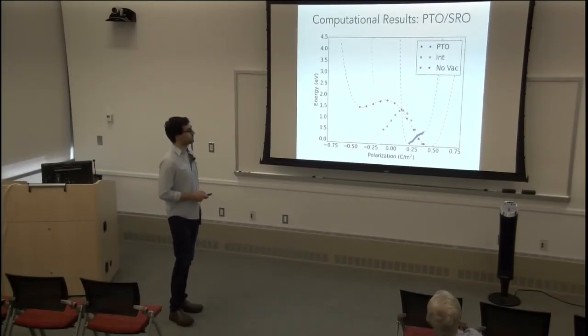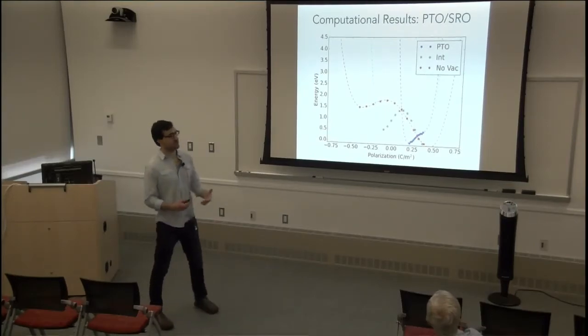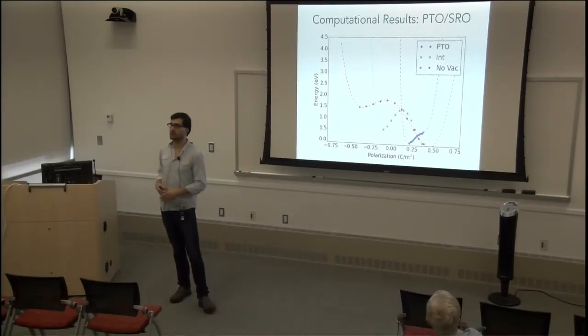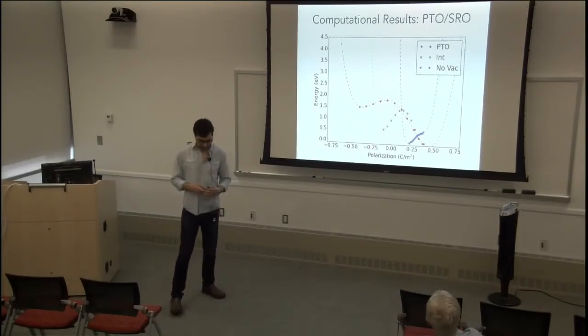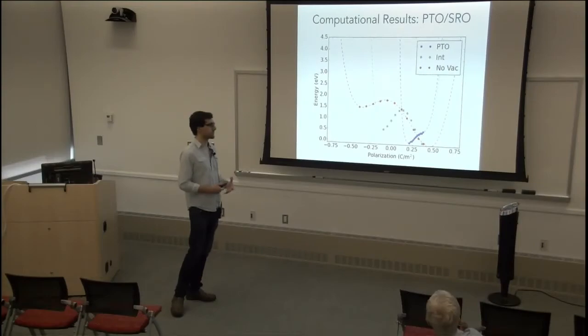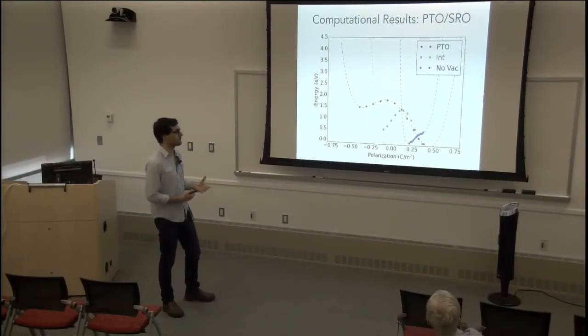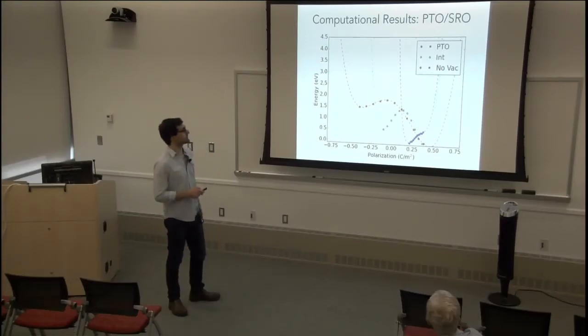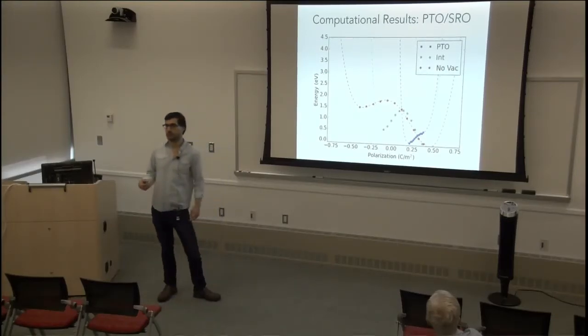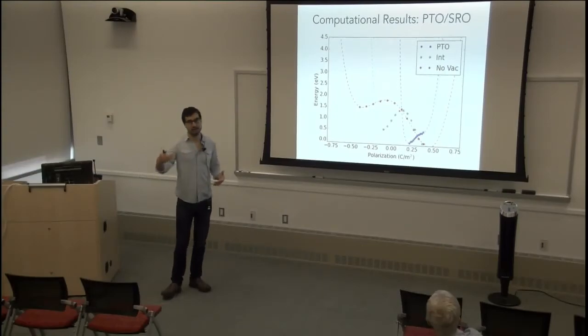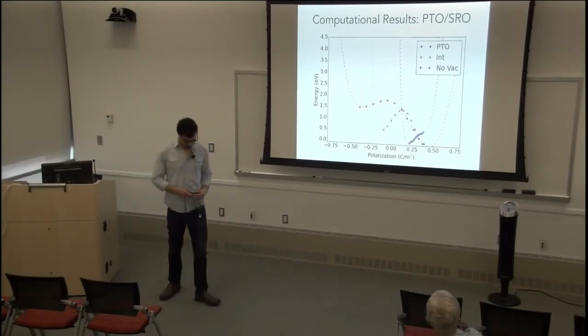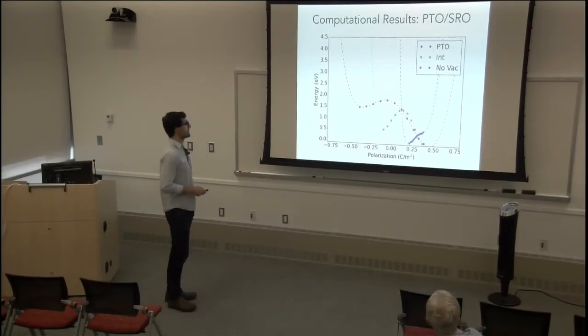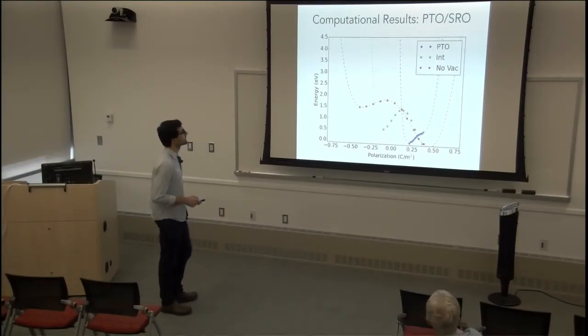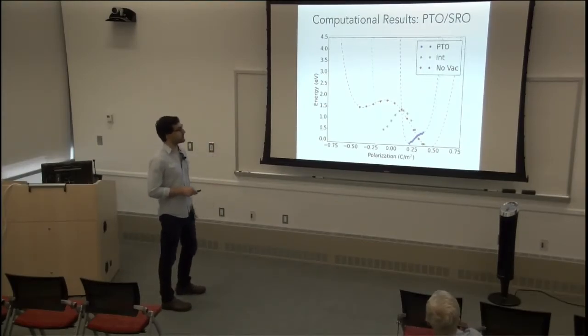This has to do with possibly two things. The first thing is that the concentration of divacancies in our simulation is an order of magnitude higher than it is experimentally because of our constraints to being able to complete these simulations. Another thing, all these simulations are done at zero temperature, whereas in principle, these materials are grown at high temperature and they're at room temperature. And that, of course, will change the phase space. So what we think is that this is correct from the simulation point of view, but this is not something that actually corresponds to reality.